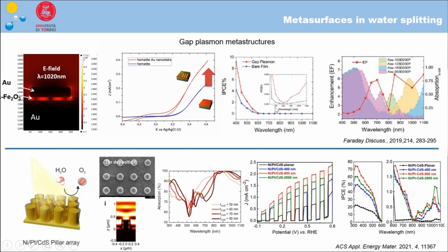The mechanism behind this, you can see from the IPCE, the incident photon to current efficiency, the action spectra. Here we measure the photocurrent at each wavelength, and then we calculate the efficiency. You can see that the highest increase is below 600 nanometers, meaning within the band gap of the hematite. We also have a small contribution to the enhancement at longer wavelengths, which is due to the localized surface plasmon resonance and gap plasmon resonance of the structure. In particular, that mechanism is due to hot carrier injection. But the highest effect is the scattering or light trapping effect created within the hematite, exciting the electron-hole pairs generated by the interband transition in the hematite.